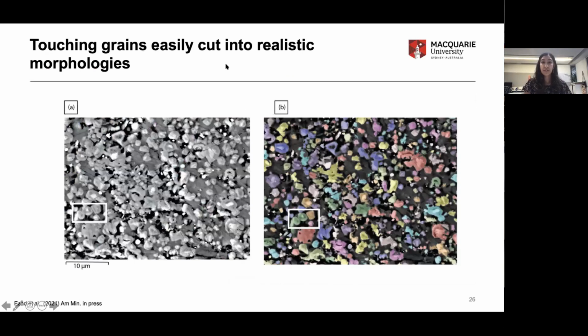So just to show you a few more examples of how well the code performs, touching grains are easily cut into realistic morphologies. If we just zoom in on this group of 3 here, you can see that they've been segmented and we've not actually lost any grain boundary material, which is really important because that would change the grain size or the average diameter, which we're interested in at the end.